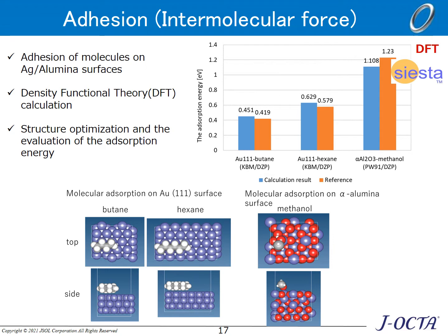The results shown here are for the adsorption of butane and hexane on gold and methanol on alumina. The capture diagram shows the stable structure during adsorption, and the top right graph shows that the results compare reasonably well with reference values. The blue color is the J-OCTA result, and the orange color is the reference value.